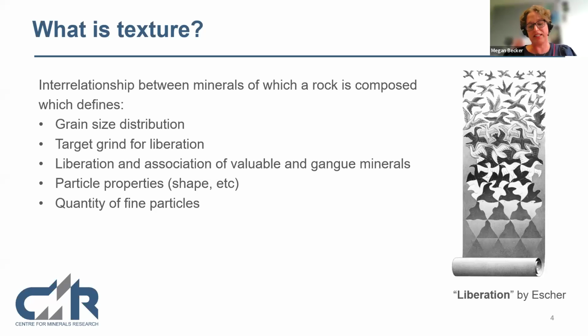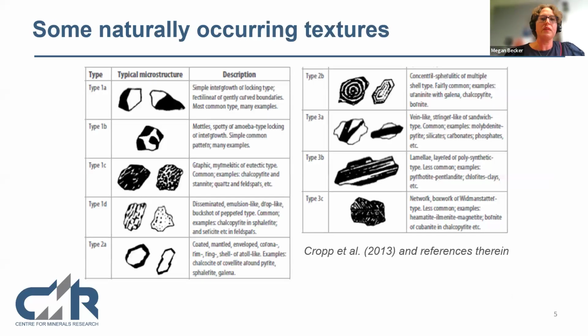But for some rocks, and something like the case study I'll show you later, which is based on chromite. Chromite as a mineral tends to have these golf balls, and it's got a very sugary type of texture. And when it breaks, it just keeps making more little golf balls. And so that is a function actually of the inherent texture. And then also it's going to determine the quantity of fine particles in addition to the breakage mechanisms. If you have minerals that are naturally very fine-grained, that's also going to play a role.